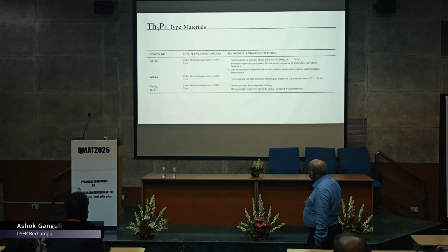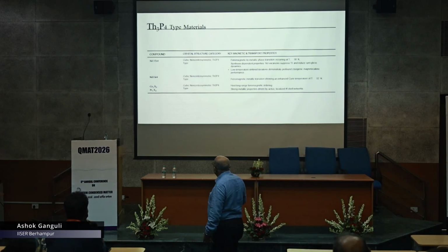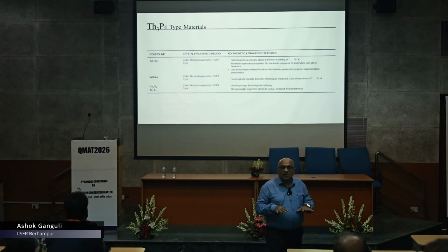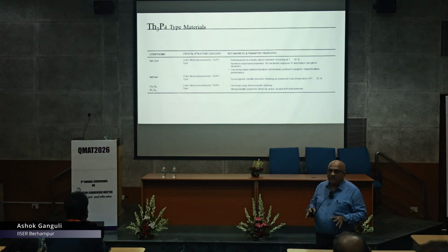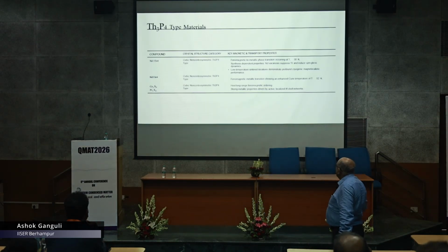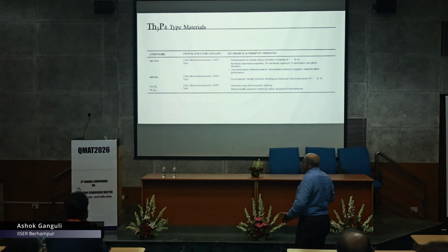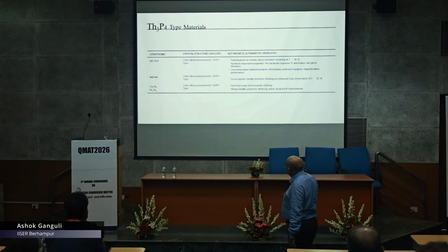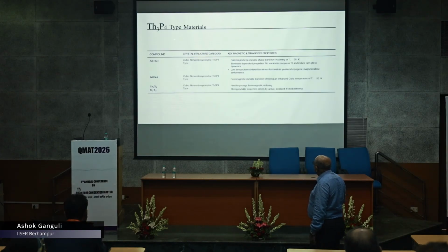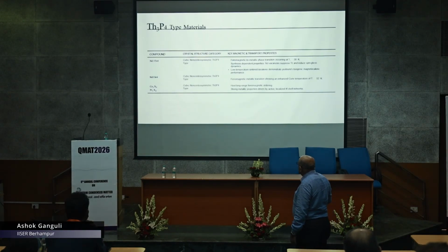R3M4, where M here is selenium or tellurium. So these kinds of compounds are forming, but they are not layered. They are 3D structures. They have a cubic space group, and they can be made superconducting. They are ferromagnetic, depending on the rare earth material. You can get from ferromagnetism to superconductivity in some of these compounds.